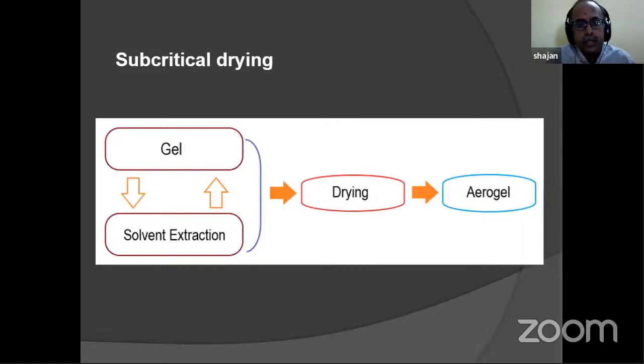The thing is, the liquid that you are using to extract the solvent should have surface tension less than the solvent. That you have to decide. So if you continuously do like that, all the liquid which has higher surface tension will slowly be removed out of the pores. The thing is, this cannot be done in a single stage. You have to repeat and repeat several times. And finally, by trial and error, you can find how many times. In our case, we did it 6 times.